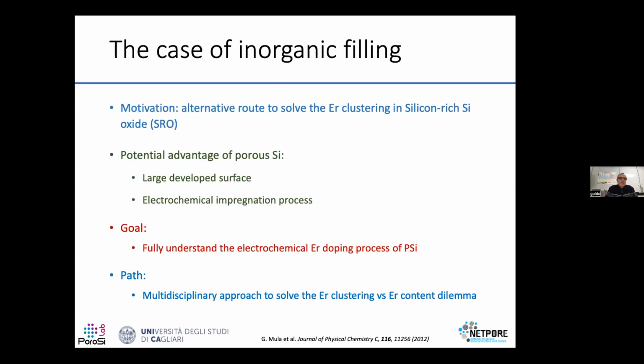So let's start with the erbium in silicon. The main problem is that erbium has a clustering attitude. So when you try to increase the erbium content to have infrared light emission, you will have in return erbium clustering that will hinder the light emission. So the use of